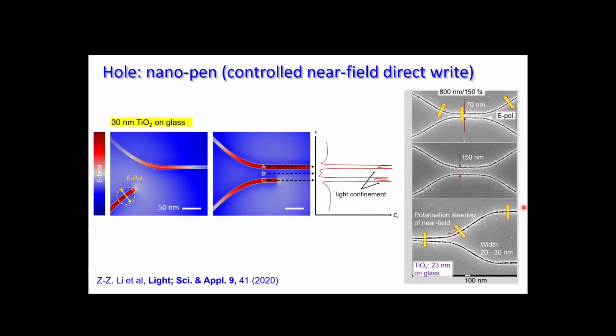If you compare with the usual lithography, you always need to recalculate your exposure dose, because the region between two features is overexposed by secondary electrons in the resist. But here, just by the same rule that you have for a normal component, the electrical field should be lower in your resist, so to speak, in titania here, and it's concentrated in your nano groove. So with the right intensity, which is 80% lower than your nano hole, you can steer it and write, and you can pattern areas just by direct writing.